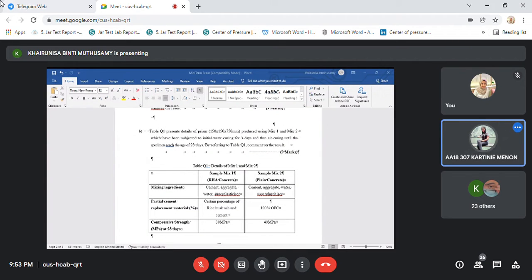Next, when the added rice husk ash is not up to the optimum level, it will never contribute to the strength of concrete. Second, the rice husk ash needs to be burned under high temperature to reduce the LOI level. And also the rice husk ash has to be ground finely. This is because the specific surface area of the rice husk ash added affects the strength of concrete as well. Only finely sized particles will develop pozzolanic activity. So by doing all this, it will help to increase the compressive strength of sample mix 1 as early as 1 and 3 days. Yeah, that's all. Okay, thank you.